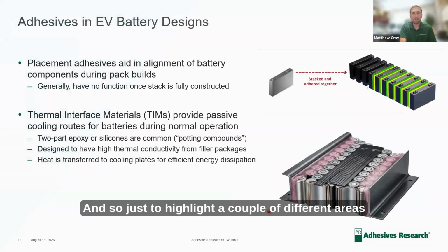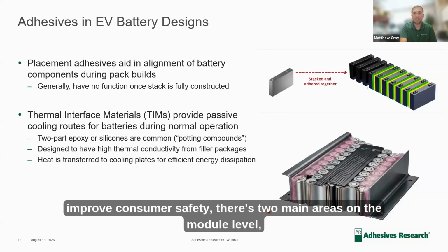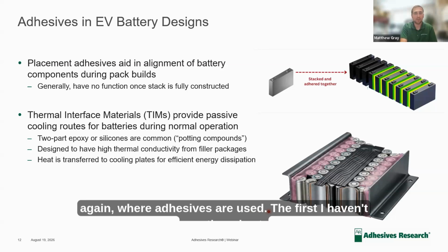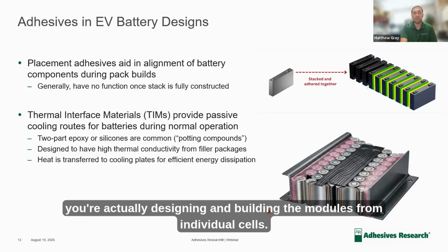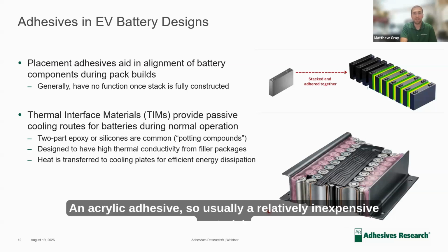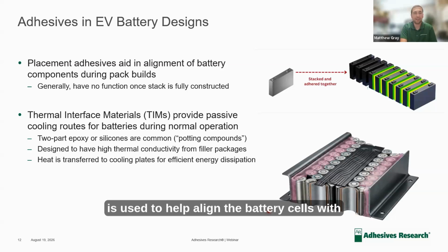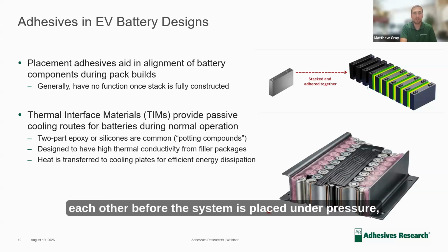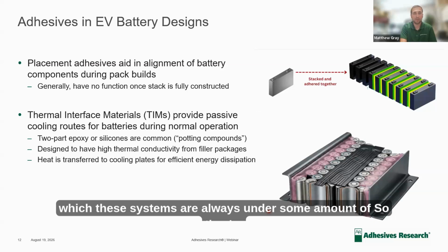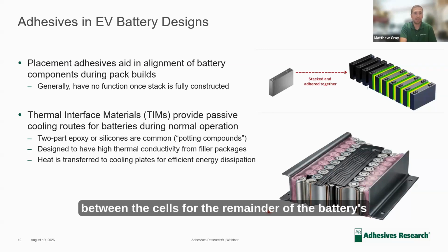And so just to highlight a couple of different areas within these EV battery modules where adhesives are used and how we are able to use our adhesives to help improve consumer safety. There's two main areas on the module level, again, where adhesives are used. The first I haven't mentioned yet, and it's actually an adhesive that has one function only. When you're actually designing and building the modules from individual cells, an acrylic adhesive, so usually a relatively inexpensive material, is used to help align the battery cells with each other before the system is placed under pressure, which these systems are always under some amount of pressure. So they're used for this one application, but then they sit ambiently between the cells for the remainder of the battery's life and really don't have a function following that.